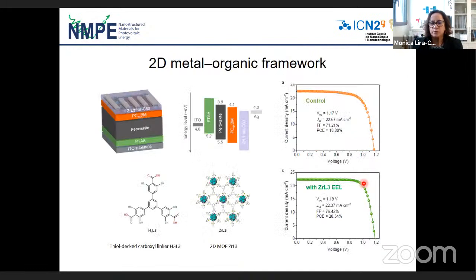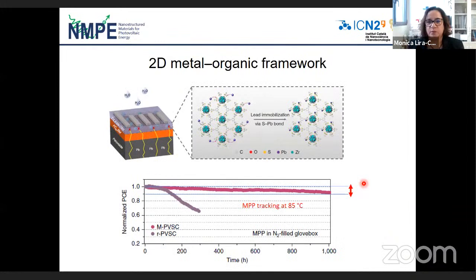I just want to show you some examples in the literature. This is a very nice example, somebody published it last year. Our next step is to try to do this stability study at higher temperatures, since all our analysis were at room temperature, and using very different techniques. This is a very good example: they only have less than 10% degradation after 1,000 hours, and that's at 85 degrees, okay?